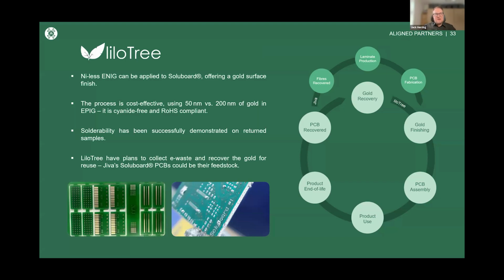This is because of the high temperature and harsh processing of the nickel application process of this standard finishing, which is the step before the gold is applied. So Lilotree has actually removed that step of the process. That's great for us in terms of being able to offer this finishing to our users. But we're also able to reduce the cost for them. We're able to reduce the amount of gold which is actually applied to the material, and it's cyanide free and RoHS compliant.